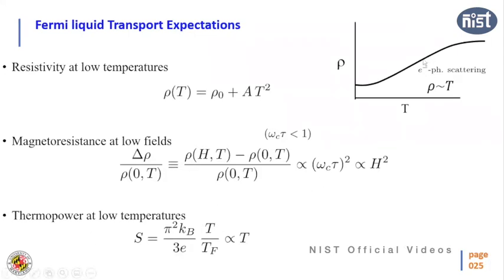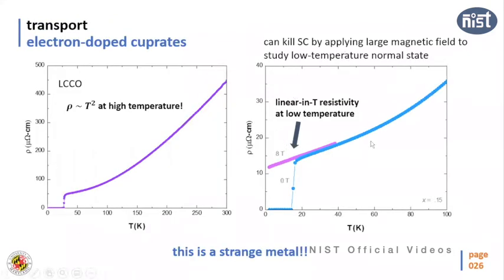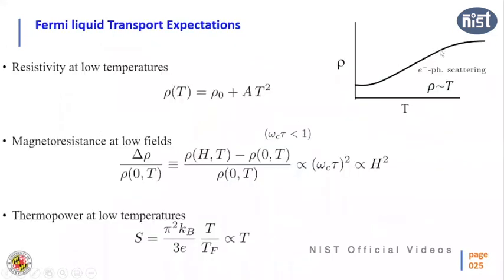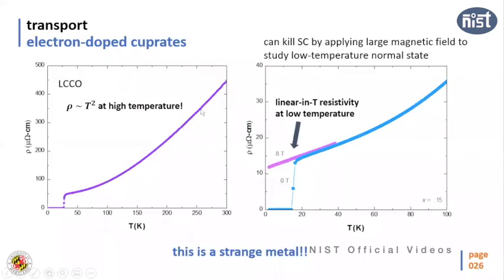Now, if it is a conventional metal, we know there are well-established theories which can explain all this and the scattering mechanism as a function of temperature. Now, what happens to these high temperature superconductors? What we found, if you take this LCCO or any electron doped superconductors, resistivity as a function of temperature in all these regimes is T square. What one would expect in this regime, because of electron-phonon scattering, should be linear. Instead of linear, it is T square. So this behavior is quite strange.